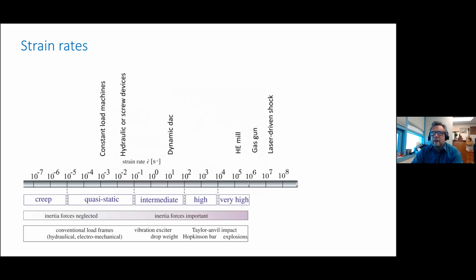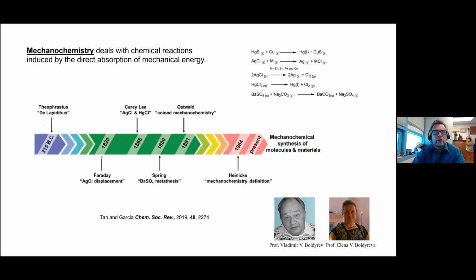If you look at the diagram that shows the different strain rates accessible in different experiments and controlling different types of behavior, you can see that high energy ball milling gives us access to much higher strain rates than are available in devices such as dynamic diamond anvil cells, not quite as high as gas guns or laser-driven shock experiments, but still it's a very simple experiment where you can work with a large quantity of sample. You retrieve all of the sample afterwards, and there's a lot you can do with it, starting from microscopic experiments for chemical analysis and so on.